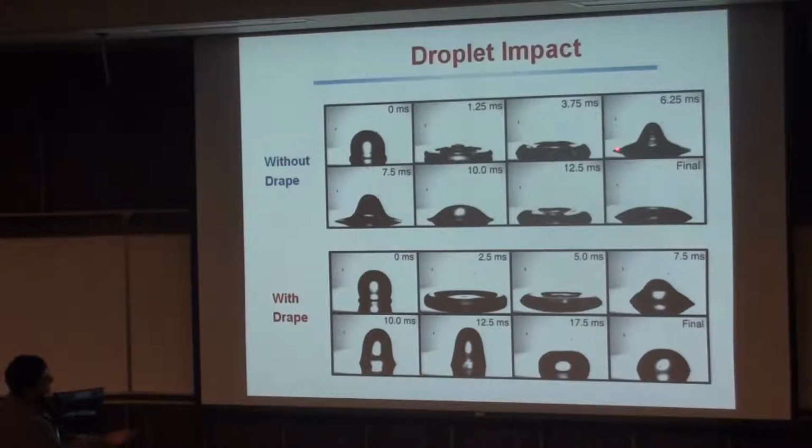So if you look at the contact length here, the contact length is not changing. That's because the droplet hits the surface, spreads, but then it's not able to recede, right? And so it's essentially stuck to the surface. So the contact line gets pinned over here. Okay? So this is a big problem on a range of rough surfaces. It's very difficult to move water drops if this happens.